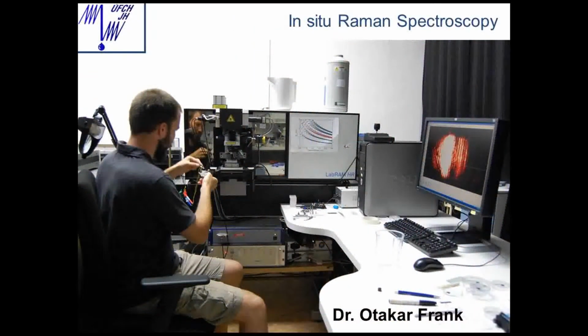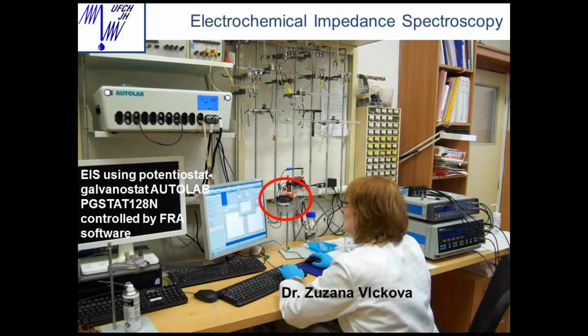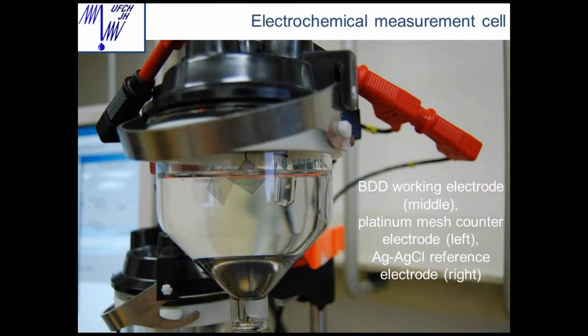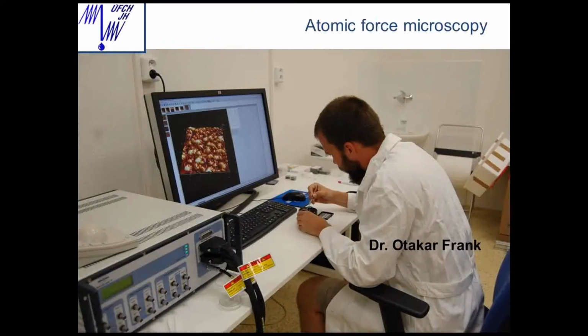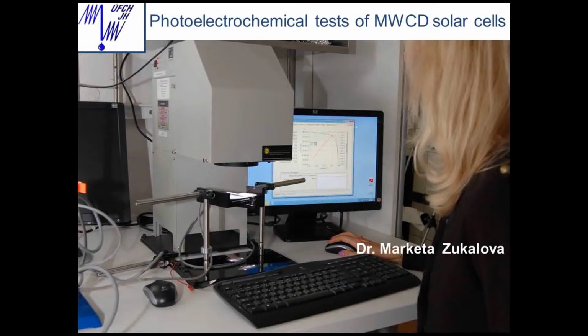Raman spectroscopy is a very suitable tool for physical characterization of boron-doped diamond films, non-diamond carbon impurity phases, and boron doping levels. Electrochemical impedance spectroscopy helps to define what is happening at the interface, surface optimization and quality control. The surface morphology was evaluated by tapping mode atomic force microscopy. Finally, molecular wire coupled dye-sensitized solar cells were tested by photoelectrochemistry.